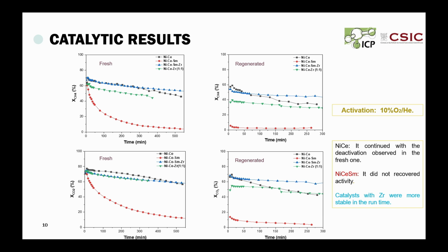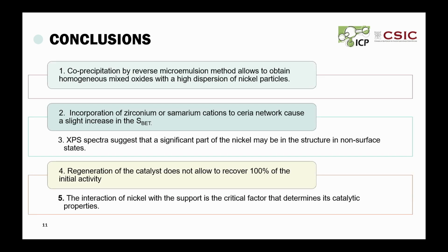That indicates that the deactivation is not only due to the deposit of carbon, but also to the modification of the structure, in this case the sintering of the catalyst that we can observe in the SEM, TPO, and XRD that we made for the post-characterization of the catalyst. So the main conclusion that we obtain is that the interaction of nickel with the support is the critical factor that determines its catalytic properties, and the zirconia could play a principal role in that activity.